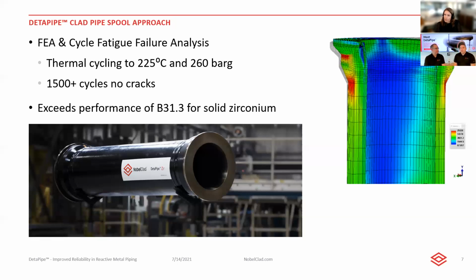So then we took it a step further and looked at the elbow solution, and said, okay, let's make an elbow and then do the same thing. And that we did back in January. We put it in test, same kind of temperature ranges, took it up and down, high temperature, back down, pressurized it, inspected it every couple of 100 cycles. And that has been running since January, still without any crack or failure. It's still running today. And right now we're at 1,500 plus cycles.